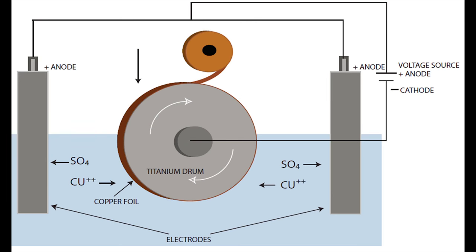What's shown in the picture here is an electro deposited process to create a copper foil. The copper foil is essentially drawn off a large drum — the drum is a cathode — and you can see the anodes as part of an electrolytic plating process. This process is very efficient; they can peel the foil off at the right rate to achieve the desired thickness. This type of process gives ED copper a vertical grain structure.